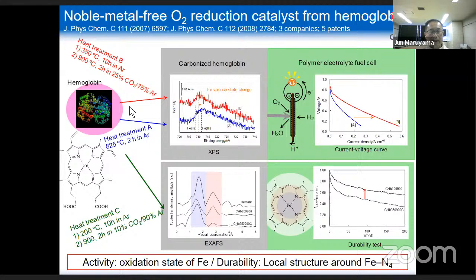If we change the carbonization conditions, different types of iron are included in carbon materials. That leads to enhancement of reactivity. And if we change the heat treatment conditions, we can get different iron nitrogen structures, observed by X-ray absorption fine structure spectroscopy. These catalysts have different stabilities.